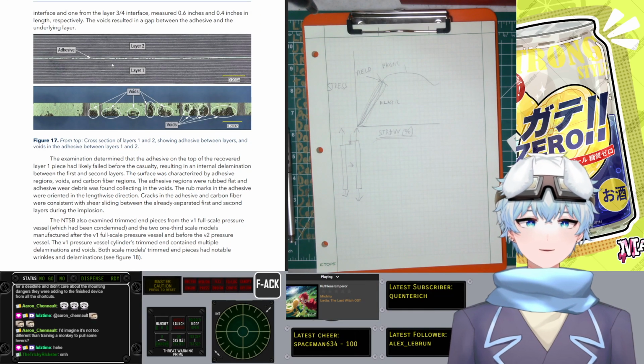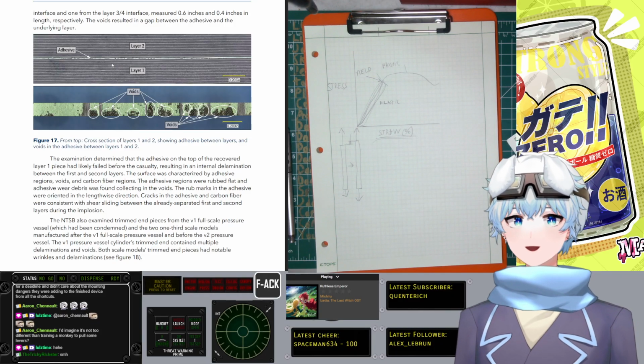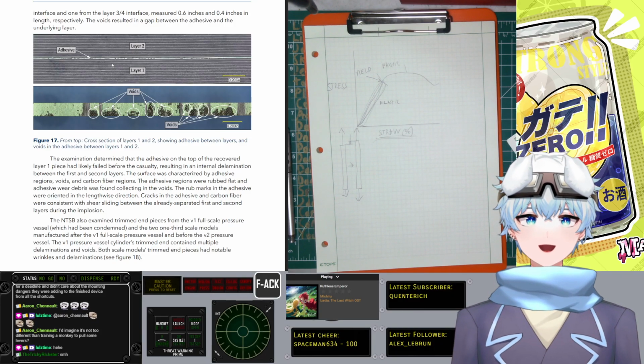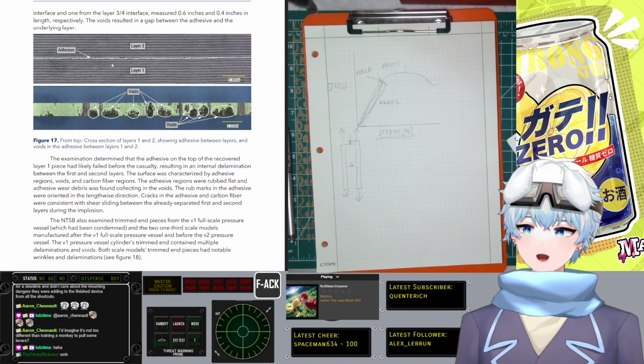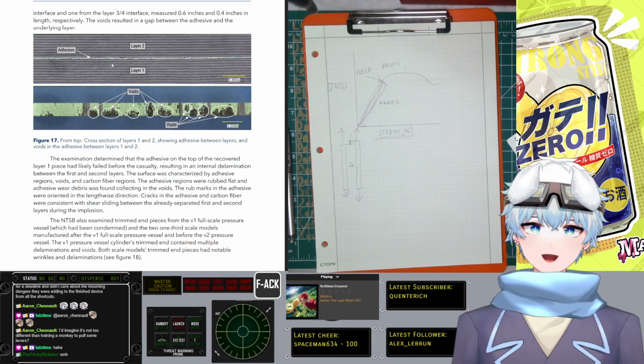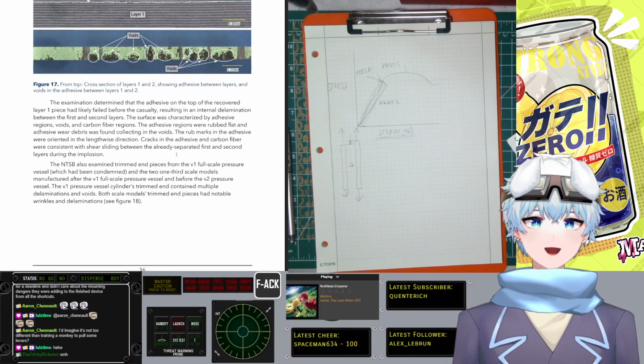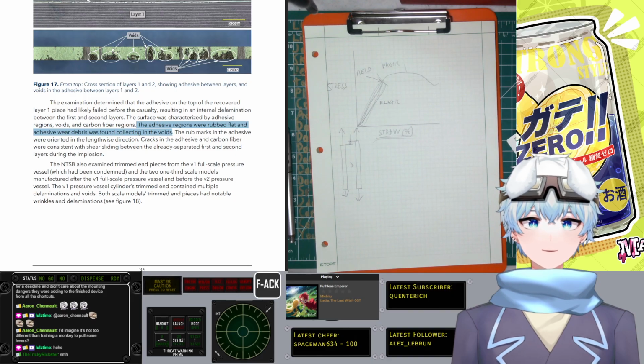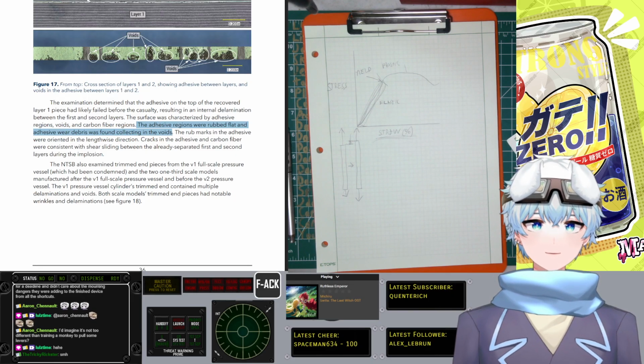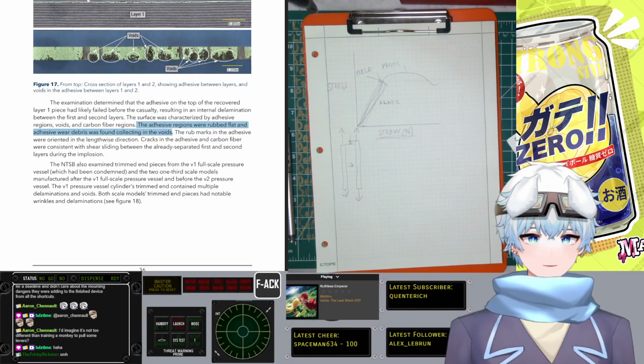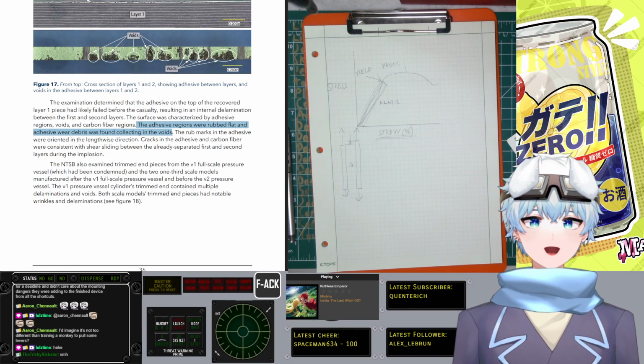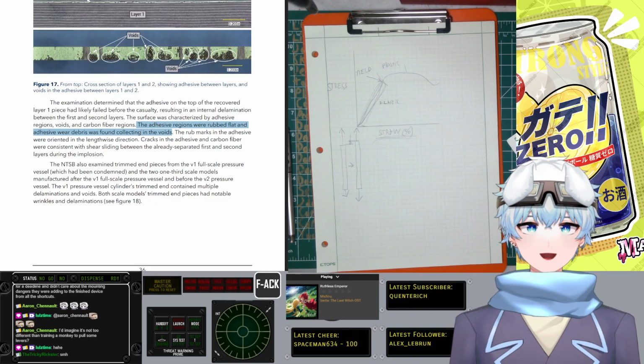If you don't have these perfectly adhered, or at least adhered well enough that they don't move relative to each other, they're going to start moving relative to each other, scraping across each other, and weakening each other. Which, as the NTSB found, the adhesive regions were rubbed flat, and adhesive wear debris was found collecting in the voids. Yep. Cracks in the adhesive and the carbon fiber were consistent with shear sliding between the already separated first and second layers during the implosion. Yep.